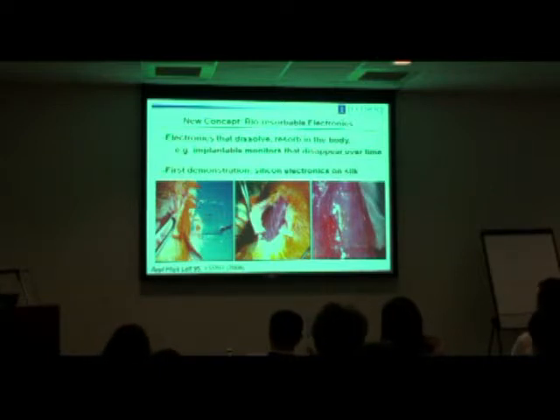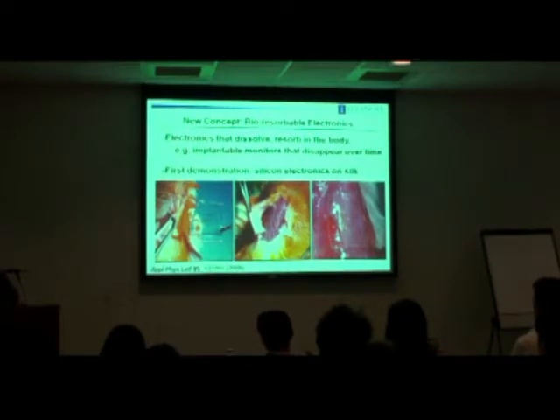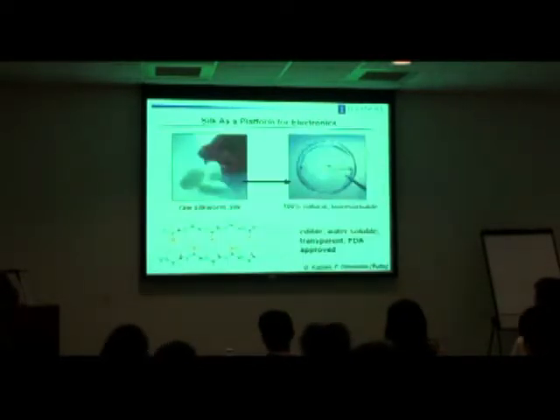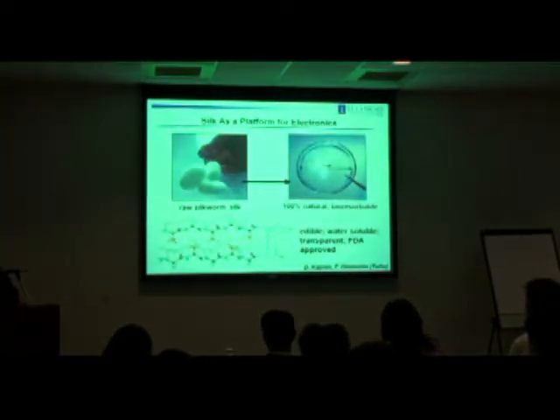If you make electronics, in this case, it's partly non-resorbable silicon devices here, and partly resorbable silk. So you can actually insert this into an animal. Over a course of months, the silk disappears, just leaving small pieces of silicon. So the idea is you could perhaps design this system, it's not fully bioresorbable, to eliminate any kind of adverse reaction by choosing the mass loading, the total amount of non-resorbable material, to be as small as possible. So that's a concept. I'll describe in a second how that relates to this neural monitoring application.